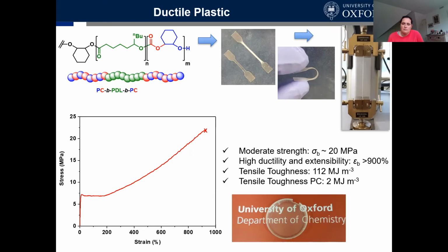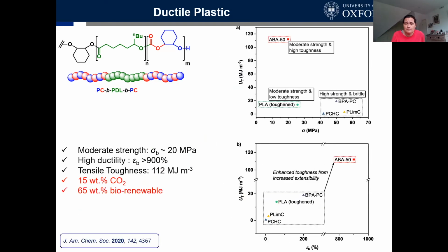So this is important because it's not brittle, and that's really a problem with a lot of the current bio-based materials, that their tensile toughness is way down in the 1 to 2 range. And actually there's the tensile toughness for commercial polycarbonate from bisphenol A, and you can see that that's a horribly brittle material as well. And as a consequence, you need to use processing aids, you need to use plasticizers to be able to apply those materials. Here, just a couple of Ashby plots where I would compare the UTS, the ultimate tensile strength, against elongation at break.